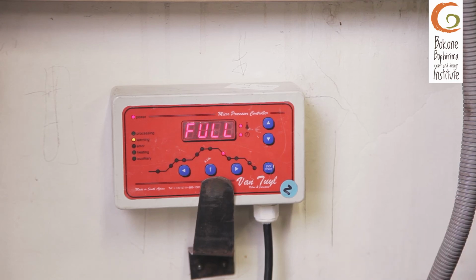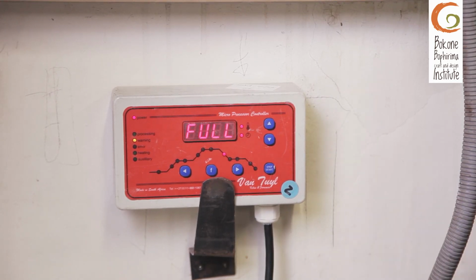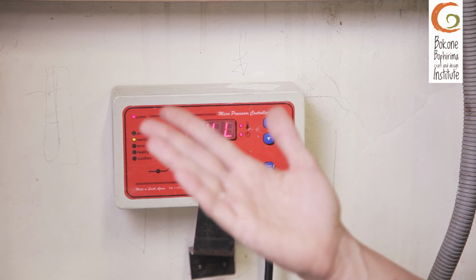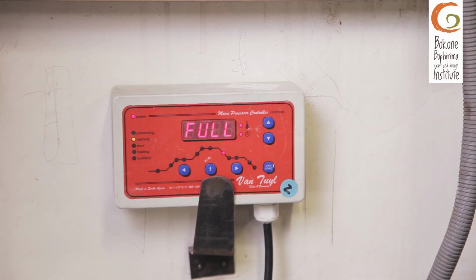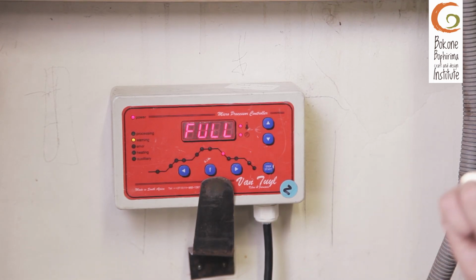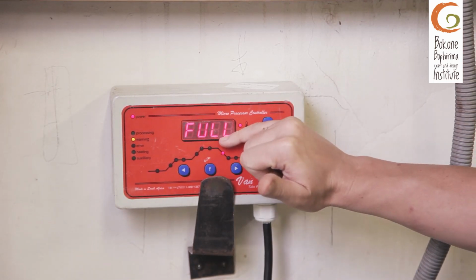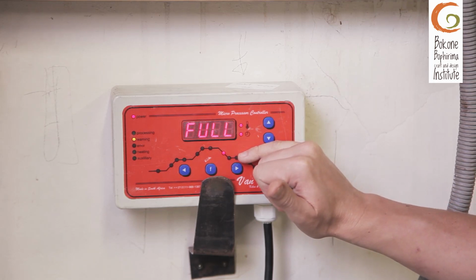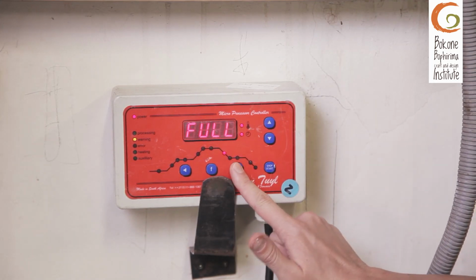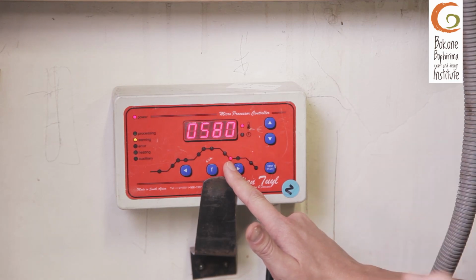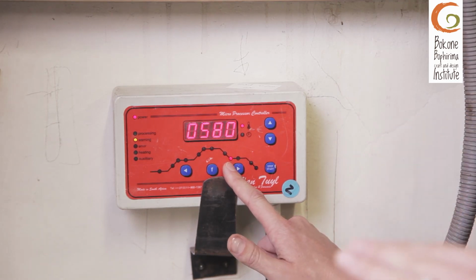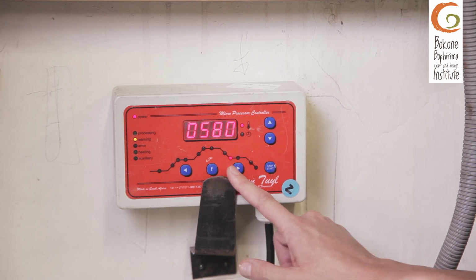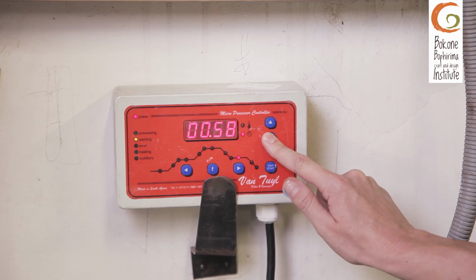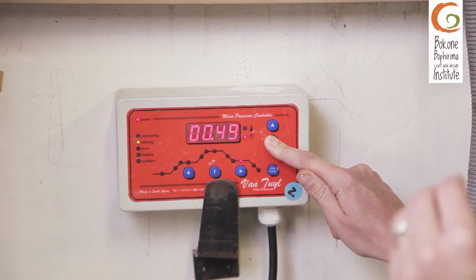So now I'm not physically going to crash cool, which one can also do. You can assist the kiln by opening up the lid and crash cooling the kiln down to 680 if you're going to manually do it. If you're allowing your kiln to do it, you need to bring it down full. So again, now I'm making my kiln go as fast as possible down, and I'm going to rather anneal it a bit lower to 580, because this is now where my glass starts becoming under tension again. And then I'm going to hold there for about 15 minutes. And why only 15 minutes is because my glass is not that thick.